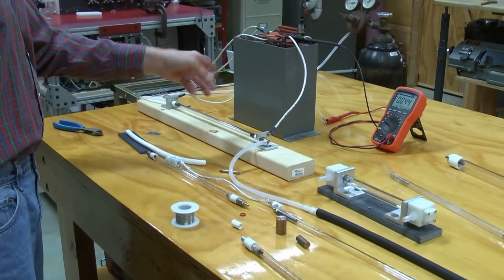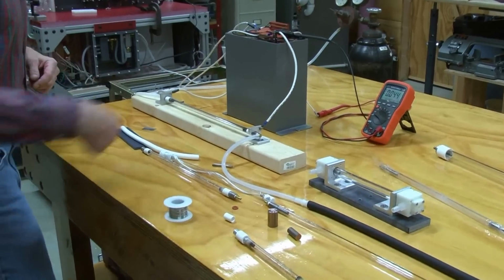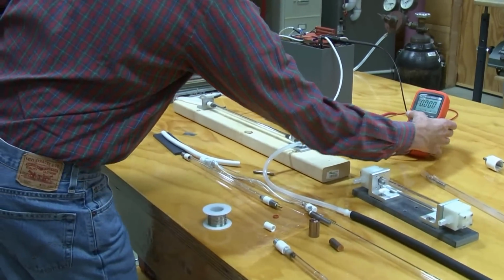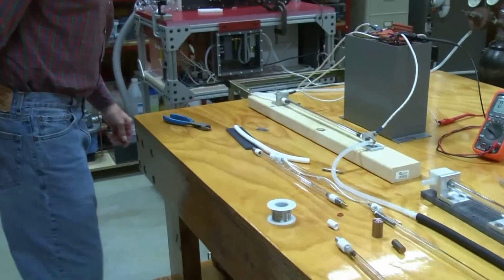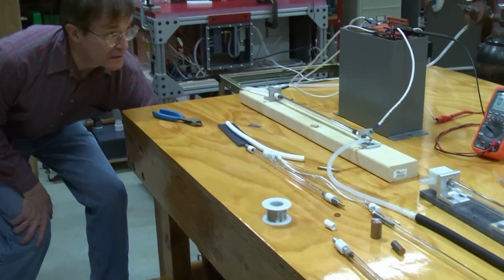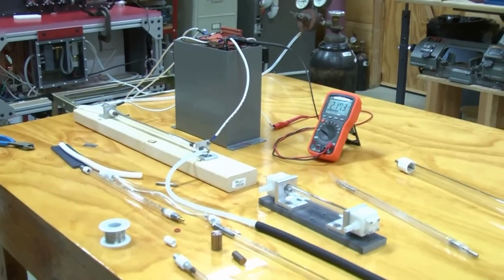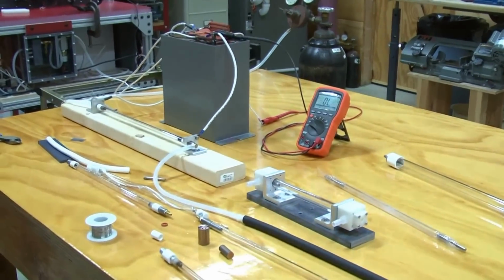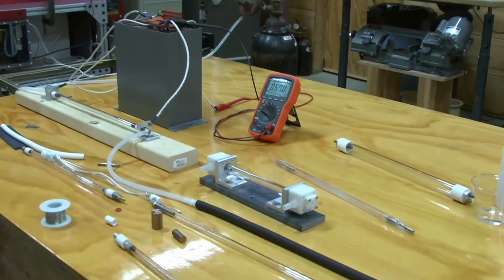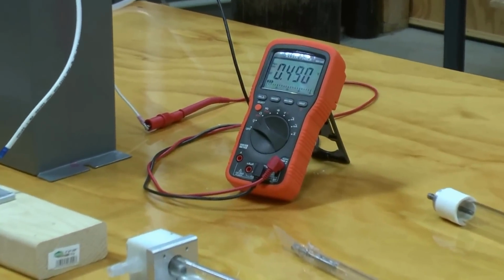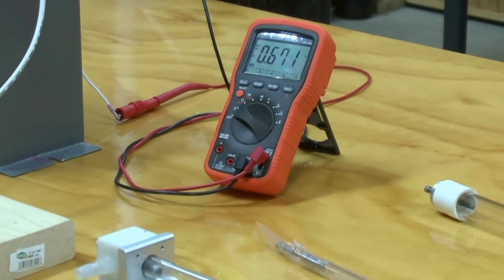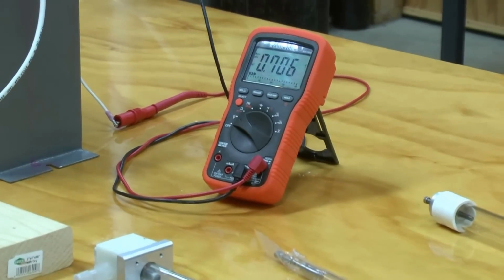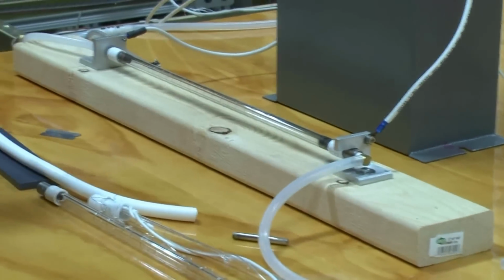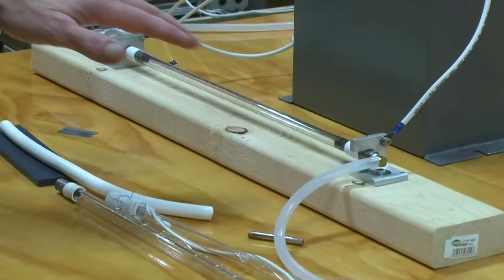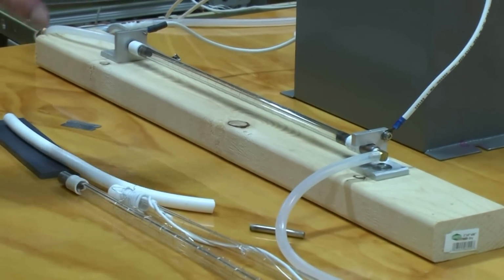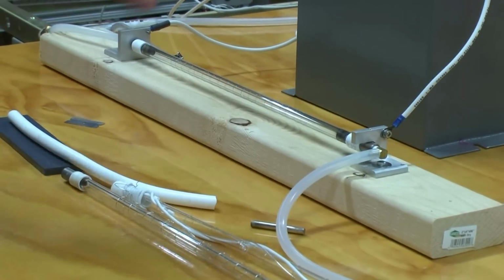Now what I'm going to do is turn up the voltage here, and eventually you'll see, it should be on DC, at about 700 or 800 volts, this will begin to discharge. About 600 volts, and you'll see the flashes. If you look carefully at that, or I don't know if you can see this clearly, but it looks bluish. It's bluish because that's the line emission of the oxygen in the system.